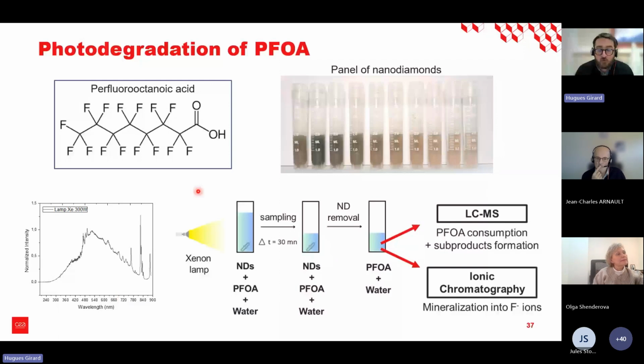What we did is that we mixed PFOA and nanodiamond in water, and frequently, every 10 or 30 minutes, we made a sampling. We removed the nanodiamond and we analyzed the remaining PFOA and all the subproducts by an HPLC mass spectroscopy system, and also we monitored the formation of fluorine ions by ionic chromatography.